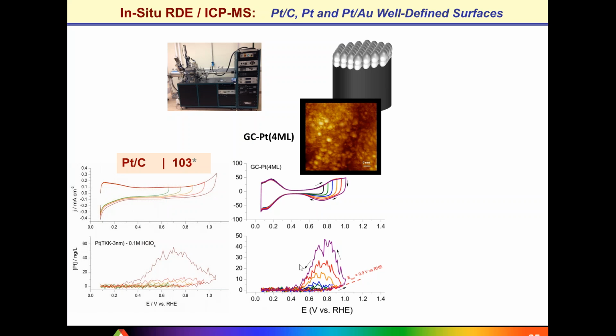So the same type of dissolution, which is not surprising considering the morphology of those thin films, highly corrugated with an average cluster size of between a few and 5 nanometers, exactly as in the case of the state-of-the-art platinum carbon catalyst. So I would say the comparison is 1-to-1 in terms of dissolution and behavior from each potential cycle, depending on the upper potential limit.